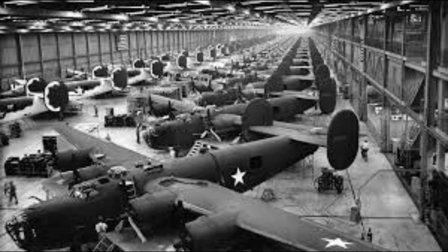The breakthrough came when engineers compared Ford's dies to those used by Consolidated Aircraft in San Diego. Consolidated used dies made from softer materials, including Kirksite, a zinc aluminum alloy with much lower hardness than tool steel. These softer dies wore out faster than steel dies, requiring more frequent replacement. They couldn't handle the high production volumes Ford planned. But they didn't damage aluminum. The softer die material formed the aluminum without scoring or gouging it. The surface finish on Consolidated stamped parts was clean, without the scratches plaguing Willow Run's production.